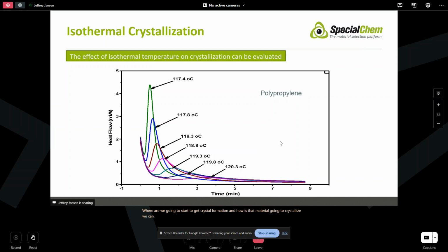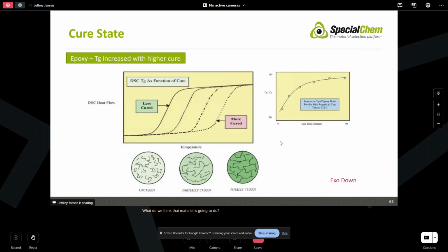We can, by running different experiments, again, isothermally, and again, we're looking at time. So what we're looking at here is, while this is cooling, and you think normally it's going to go in this direction, this is time at isothermal during cooling, okay? And so what's happening is the colder we set our injection molding tool, that's going to be a different way that those crystals are going to form compared to if we've got that higher temperature. We're going to get a more slow, uniform crystal formation out of that higher mold temperature. Again, we're also going to get a higher level of crystallinity. So again, this DSC can actually be used to get some processing information. What do we think that material is going to do? And certainly, we can also get information about thermosets.